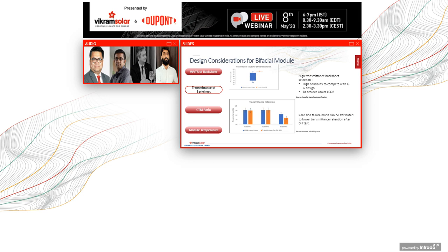But after damp heat, after humidity ingress through the backsheet, the transmittance value actually reduces. So if you see the graphic on the bottom, we talk about the transmittance values reducing by anywhere between negligible for the first two to, on the supplier 3, it has reduced by almost 10%, from 80% to about 70%, which means the bifaciality factor for this bifacial module is going to be severely impacted if you don't choose the right backsheet.